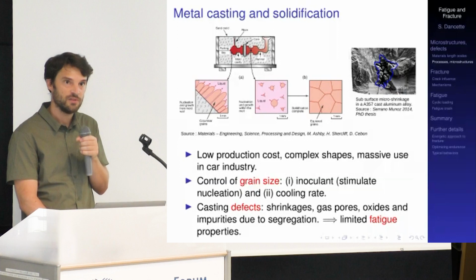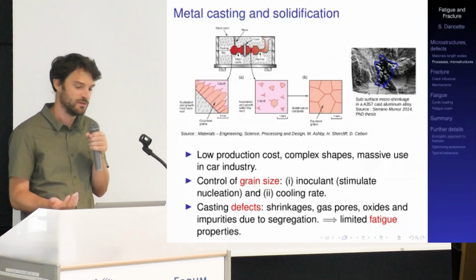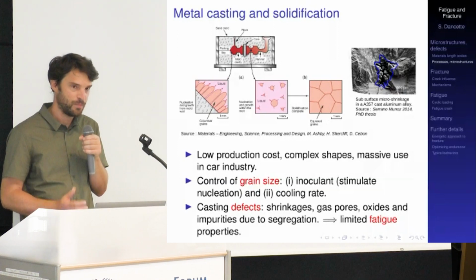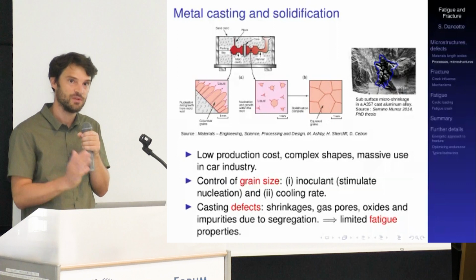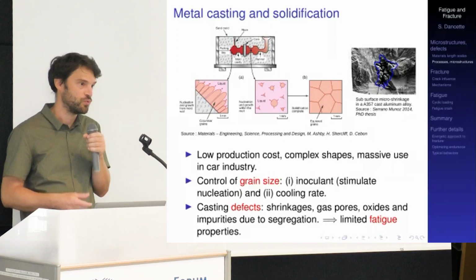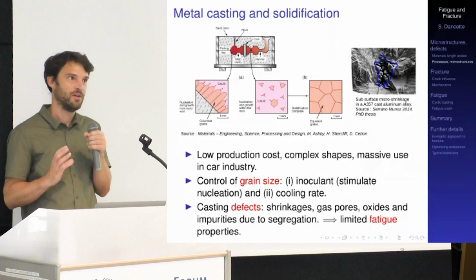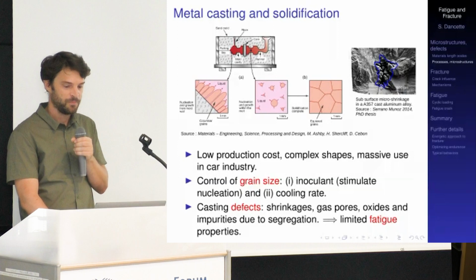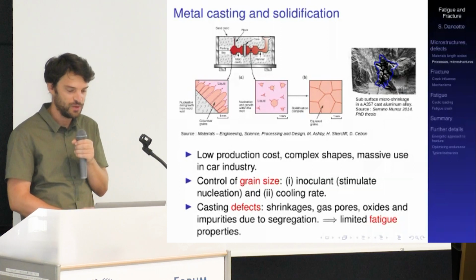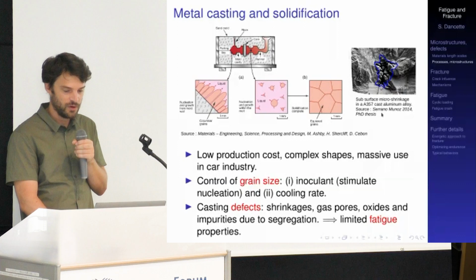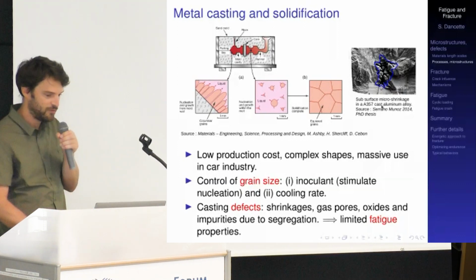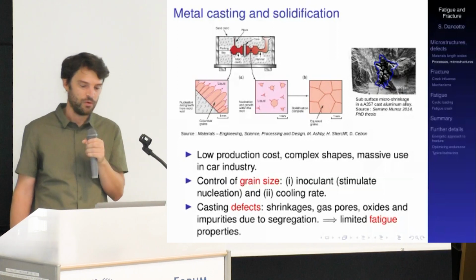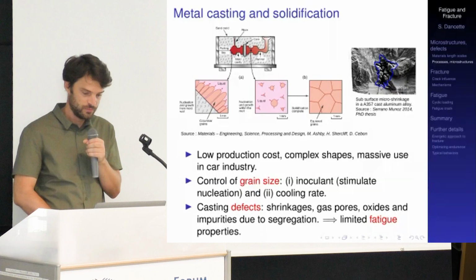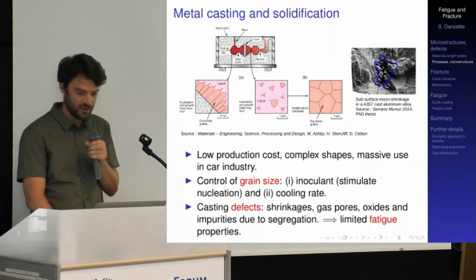And these micro shrinkage defects directly originate from the fact that there is some change in the capacity of the materials between the liquid state and the solid state. And since the whole thing has to cool down under constrained, let's say, geometry and constrained cooling rates, it is not unusual to find such kind of micro shrinkage defect in a mold, in a metal cast. So this is the example of an aluminum alloy, a cast aluminum alloy, but you may find similar defects in a whole range of cast irons, for example.